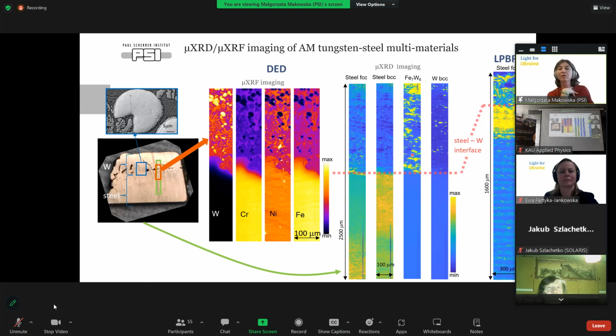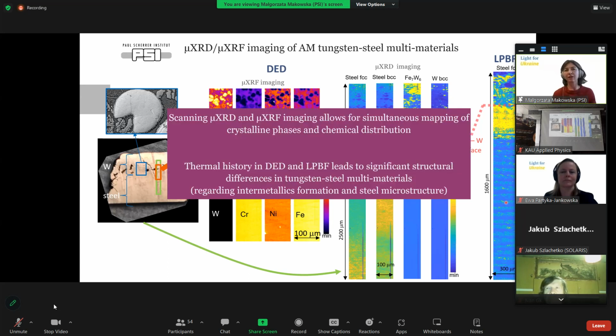And what is also important, we can see nicely the distribution of FCC phase and BCC phase in the steel part. And interestingly, this was the distribution for one technique, and for the other technique, this laser powder bed fusion, we got completely strange distribution of the BCC and FCC structures. But this is very important for the mechanical properties of such materials. And even though it was expected to have pure BCC, so